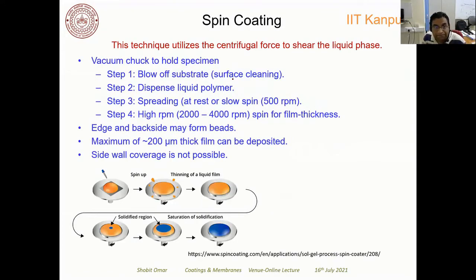Okay, so let's just talk about the spin coating technique, and you can see that you require a vacuum chuck which can hold your substrate here, and you first clean the substrate, so that there should not be any contaminant. You remove all the particles from the surface of the substrate, and then you drop the liquid phase on the surface of the substrate, and then you spin this vacuum chuck. Okay, because of the centrifugal force, this liquid will get deposited uniformly on the surface of the substrate. Okay, and the thinning of liquid film will occur.